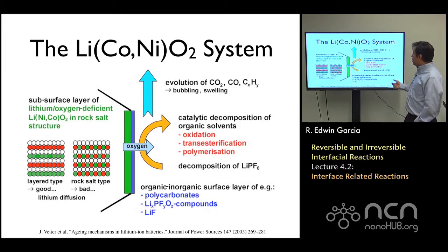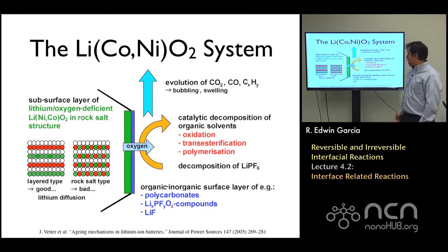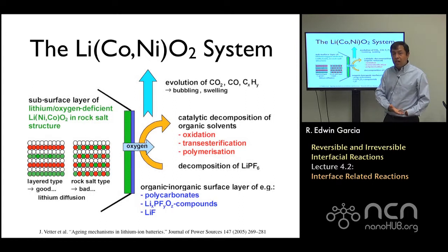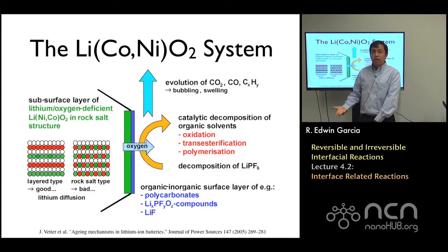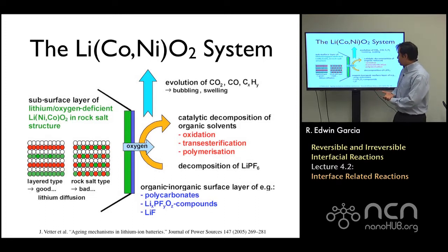Okay, and again, typically when this happens, these organic solvents may lead to oxidation, transesterification, and polymerization that could completely kill the interfacial reactions. In some cases, some of this cathode material will effectively dissolve in the electrolyte and sometimes even diffuse all the way into the anode, leading to instabilities in the SEI and poor response of the system. Okay, this is again for the lithium cobalt nickel oxide system.